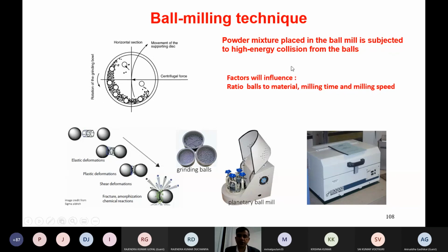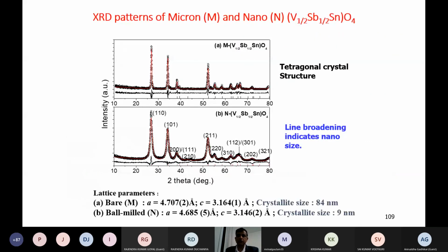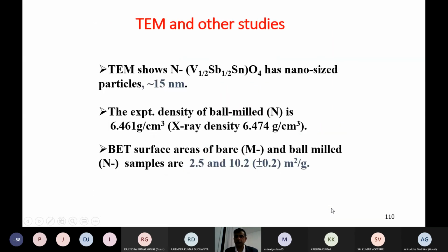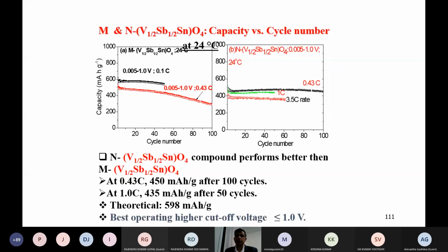People can mix the sample using agate, or depending on the material, people can use different types of balls or different types of containers to avoid contamination of the sample. So this is one example. You can tell if you go from micron size to nano size: in XRD we can see the difference in the line broadening, and we can see the difference in the crystallite size, etc. We can also check with TEM and surface area, and we can see the difference: nano size material has slightly higher surface area, etc. So this is one example.